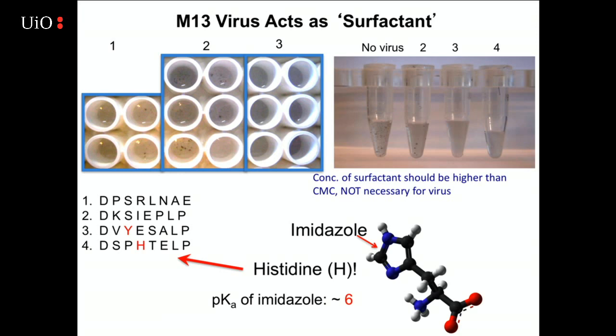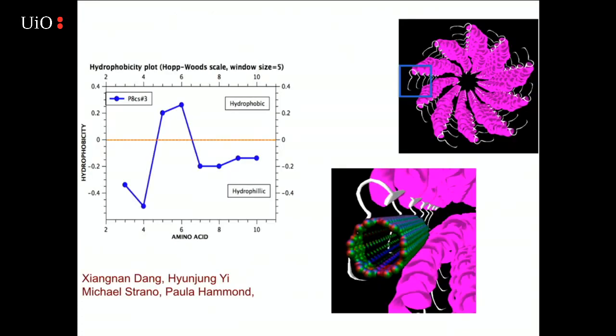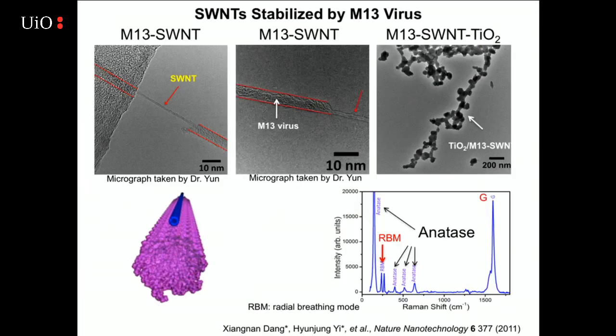And so in this case, this is basically dialysis tubing. These are different clones that they pulled out that looked like they bound to carbon nanotubes, but it was only these that actually kept them soluble. And then we looked at the different sequences of these and made decisions in terms of which ones would be best for binding carbon nanotubes and growing the titanium nanoparticles. And it acts like a surfactant, and so it was actually the particular choice that we made.